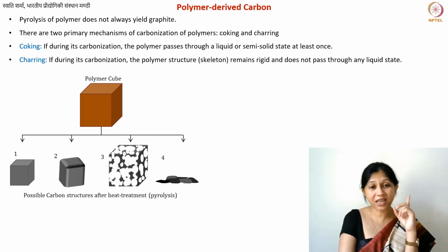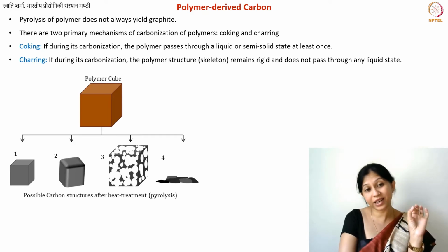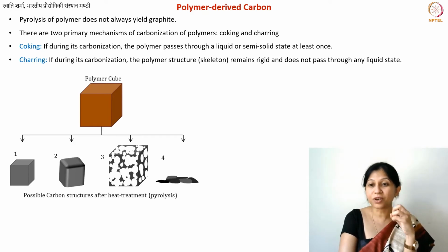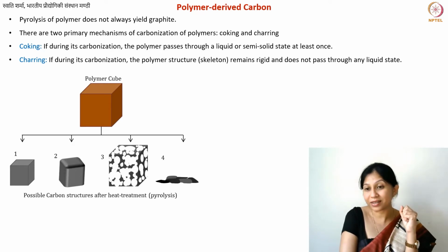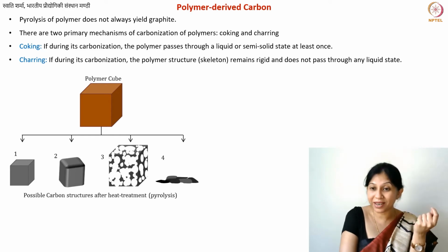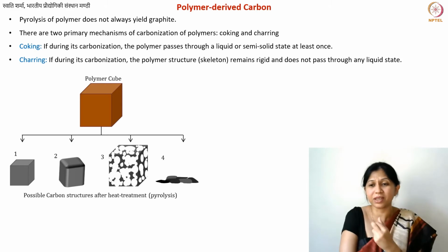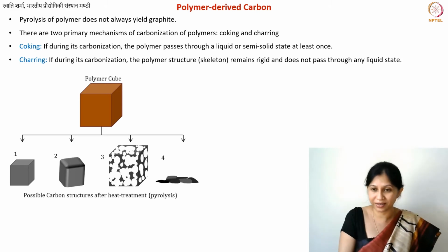But that mass loss does not necessarily create shrinkage. It will create shrinkage if the gases and the tar-like things are uniformly annealing out throughout your material. But if you have pores being created, then wherever the mass is, the structure is very rigid.